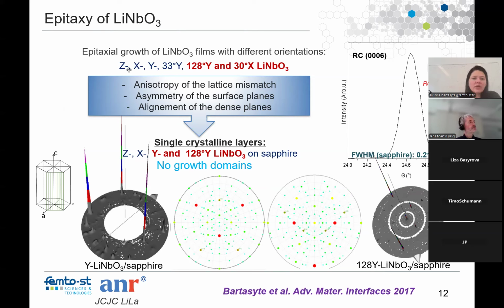So we can grow different orientations: Z, X, Y, 33 degrees, Y, 128. Now, I name all these orientations in acoustic, in IEEE notation. Of course, there are crystallographic planes behind each of these orientations. But with single crystalline quality, we're able to grow only Z, Y, 128, and 52 Y orientation as well on sapphire.